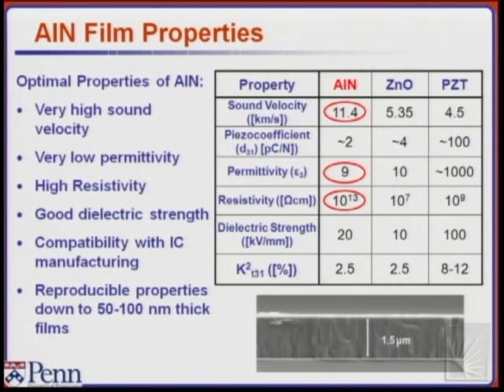At 1 gigahertz, I would have to make a 5 micron feature for aluminum nitride, whereas I would have to make a 2.5 micron for zinc oxide. If I go to 10 gigahertz, that becomes 500 nanometers versus 250. So the fabrication tolerances are at least 2x better. Then there's a low permittivity, which is another advantage over PZT. That means you don't have a giant capacitance to deal with. High resistivity is another advantage in terms of leakage. We see it as favorable, especially when we make nanomechanical devices where we want a low leak rate. You don't want to leak current through your material.